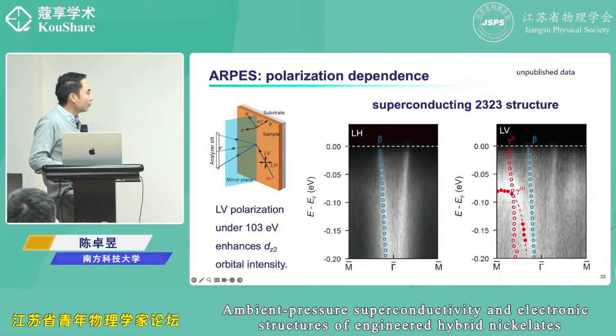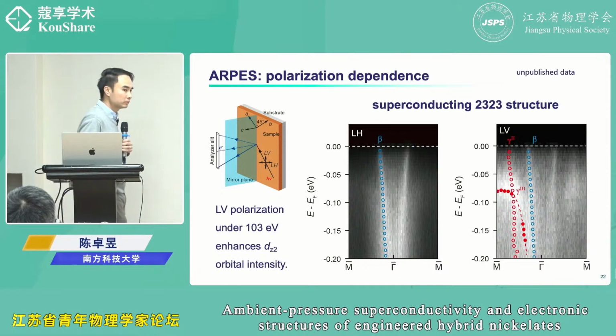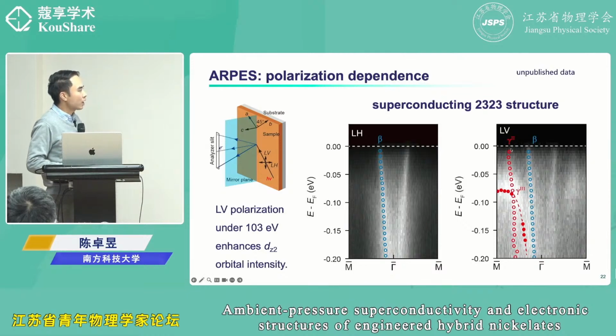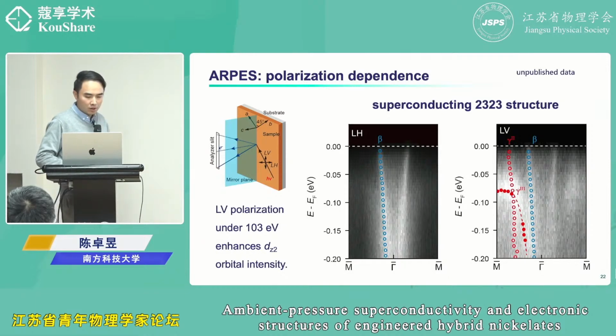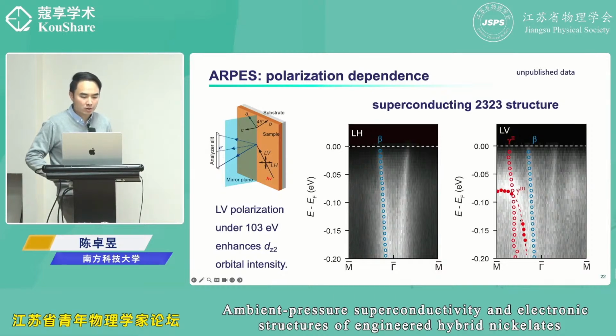You can see that both this gamma 2 that's crossing the EF and also this gamma 3 that's lying below EF are showing together. And also, when you have gamma 2 and gamma 3, are they both bonding, or is one of them bonding and the other non-bonding? Well, the exact origin needs theories to help us understand. But our very naive and simplified understanding is that gamma 2 may be coming from the bilayer structure and gamma 3 may be coming from the trilayer structure. Yeah. So also this polarization dependence between LV and LH helps us to understand that both this gamma 2 and gamma 3 are coming from dz square. Yeah, because for LV, the dz square intensity is going to be enhanced.